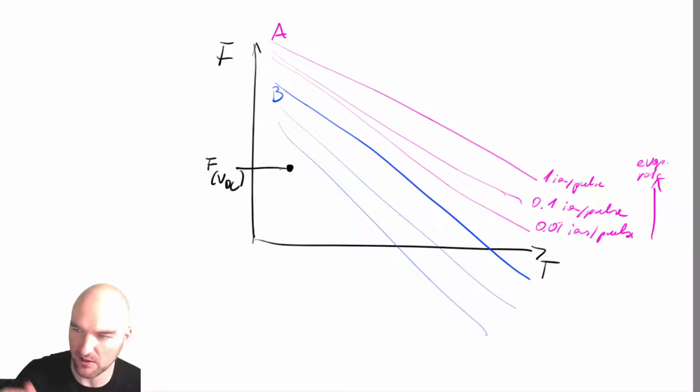We'll just impact at a random time on the detector, and we're not going to be able to say whether this was a cosmic X-ray, whether this was radioactive decay in the detector, or whatever else. We're not going to be able to tell it apart because it's not going to have any time correlation. So we need to make sure that our DC field is always low enough so that none of the evaporation is at any rate that is relevant.